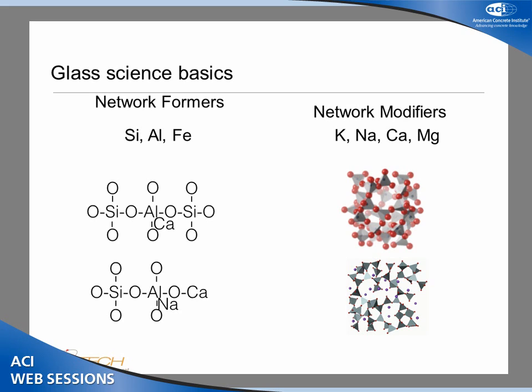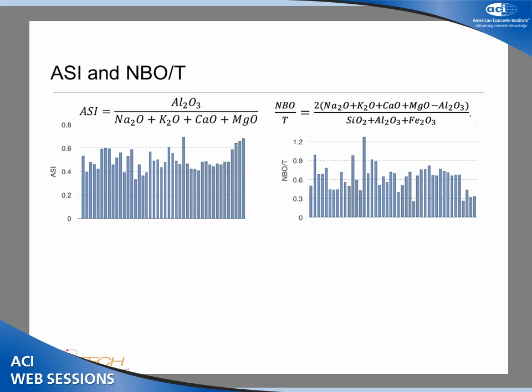And then the more network modifiers you add to your network, it starts to look more like this one. It's a more fragile network. So pretty basic formula. We calculated that from the XRF analysis once again. These were the results that we obtained. I should also mention that once we saw that we were getting good results with this, we added 18 more fly ash samples. So at the end we had 38 fly ash samples.